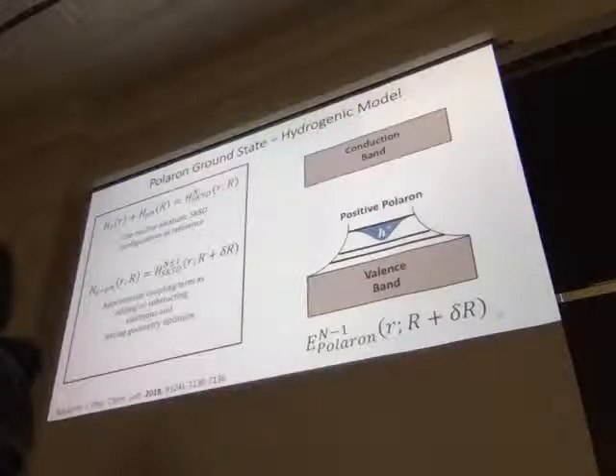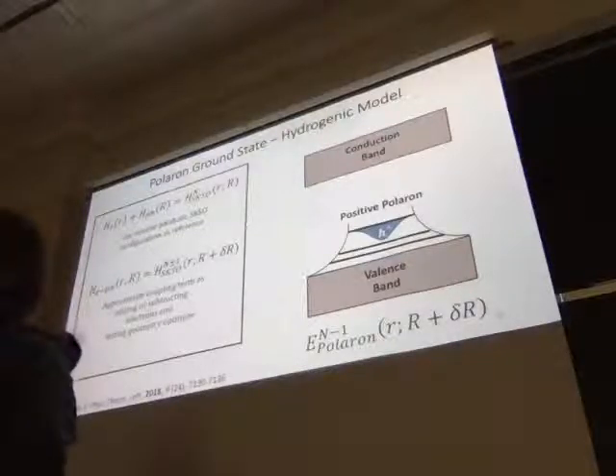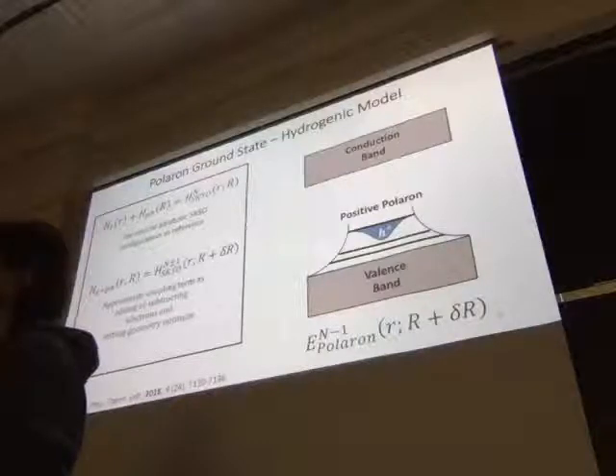Well, okay. I'm also a little bit confused about the following. When you do your density functional theory simulation combined with non-adiabatic dynamics, everything that's going on is already there. Polarons are not, and you look at the cooling and so on, and then you switch gears and talk about polarons. I guess it's just running the same machinery for adiabatic coupling, just with different charge occupations. For a charge neutral system, we wouldn't have any occupancy in the conduction band when we do our calculations for the couplings. But when we do the polaron, we occupy the lowest conduction band state, and then do the same.